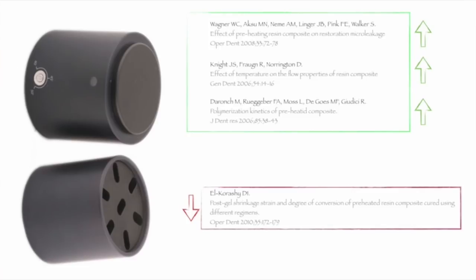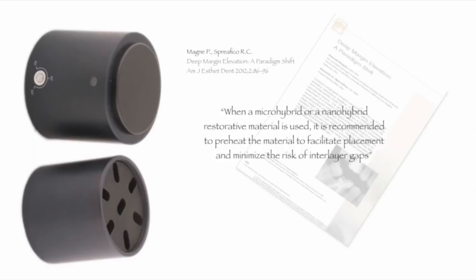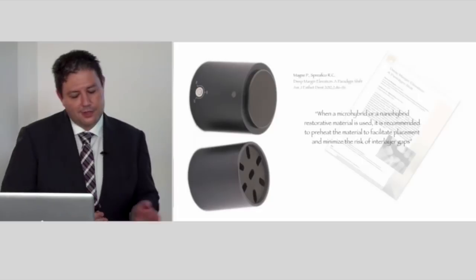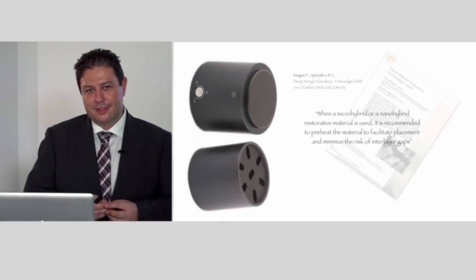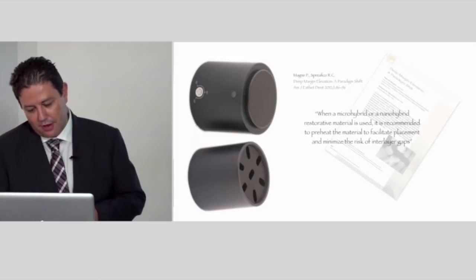So if we follow the literature and our practice, we've been using preheated materials for several years and we have had very good results. And there is an article by one of the masters in aesthetic and restorative dentistry, Pascal Magne, written with Roberto Spreafico, that says that when you use a micro-hybrid or a nano-hybrid restorative material, it is recommended to preheat the material to facilitate the placement and minimize the risk of interlayer gaps. So if Pascal uses it, let's use it because he's a reference in restorative dentistry.